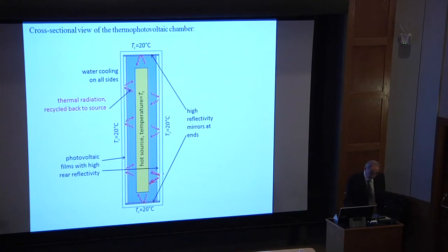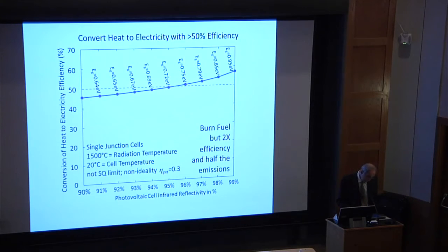So, okay, the source of heat can be any source of heat you like. I have some people at Berkeley who want to use radioactivity for the deep space probes. And so they will, because right now they're using thermoelectrics, which in no way approach the efficiency we can achieve here. So let me tell you what the efficiency could be. And it is completely dependent upon the reflectivity at the back of the solar cell. So I've combined all my parasitic losses into the effective reflectivity at the back of the solar cell.